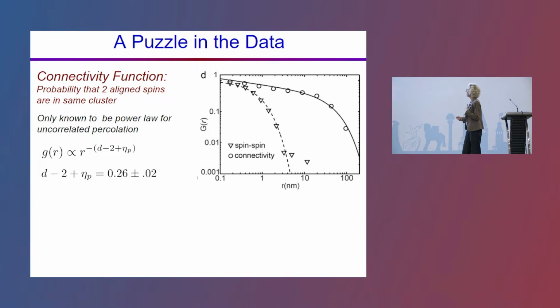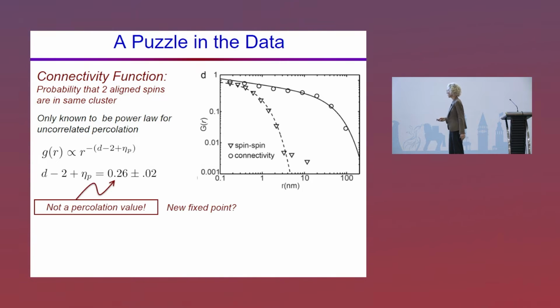the connectivity function. So this is a measure from percolation theory. It's to track the order parameter from percolation theory. So the connectivity function asks the following question. These two spins that are aligned, are they in the same connected cluster? So if the spins are aligned, can I walk by nearest neighbor steps on same color pixels all the way to that other spot? So it's a question of connectivity. And this turned out to be power law. However, it's not a percolation exponent. So this exponent that comes out of the analysis is not percolation.